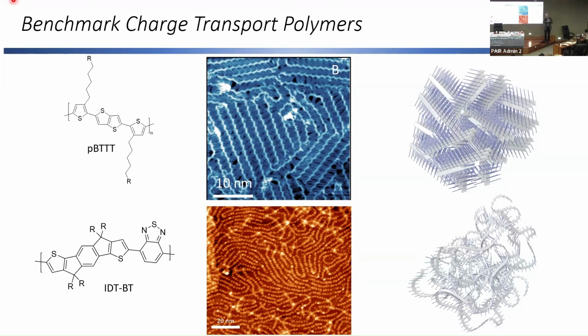So the backbones are very coplanar, and there are reasons for that related to short contacts between, actually the biggest is a non-traditional hydrogen bond between the lone pair of electrons on nitrogen and this alpha hydrogen here. And we also get sulfur hydrogen interactions and sulfur nitrogen interactions. But all of these interactions between repeat units help to planarize the backbone. And these give rise to this ribbon. So even though it's a very wavy looking polymer, the actual backbone itself is very, very planar.